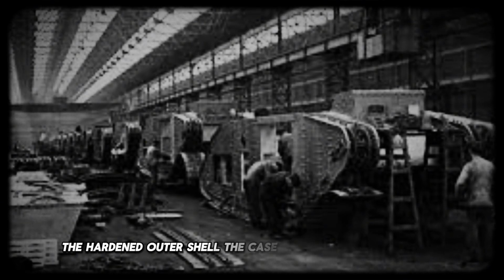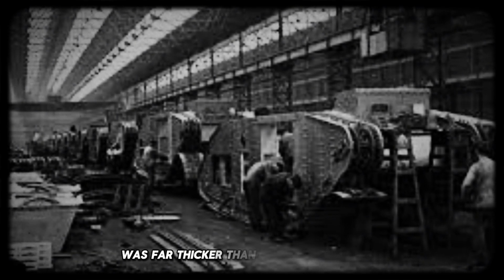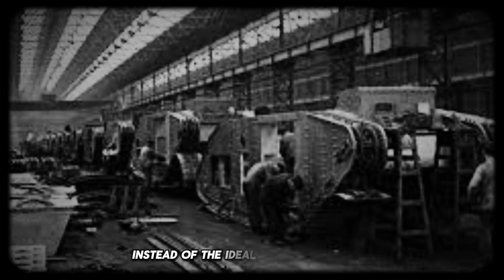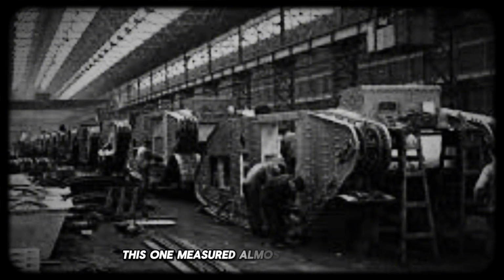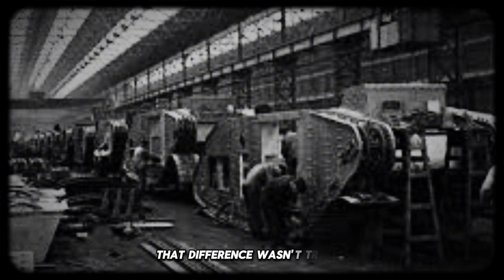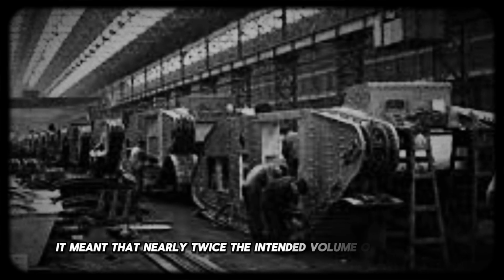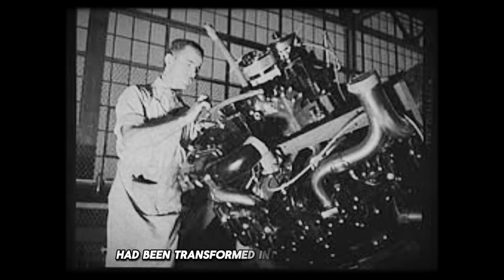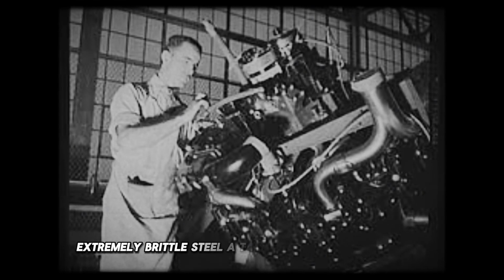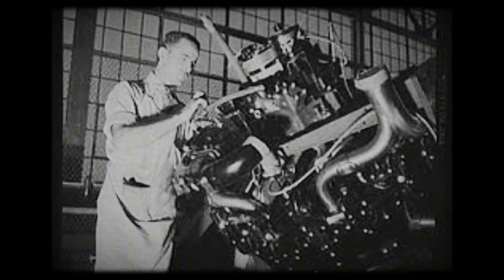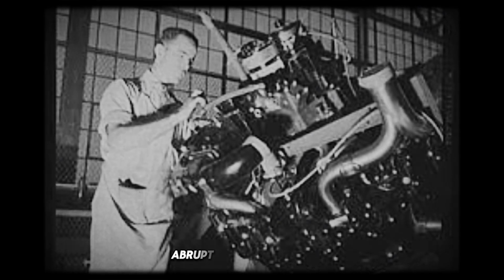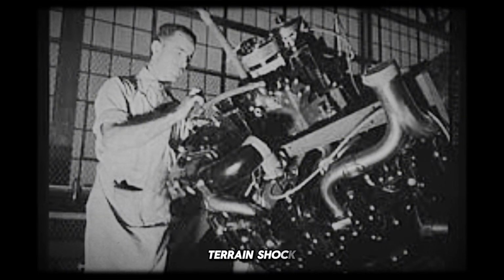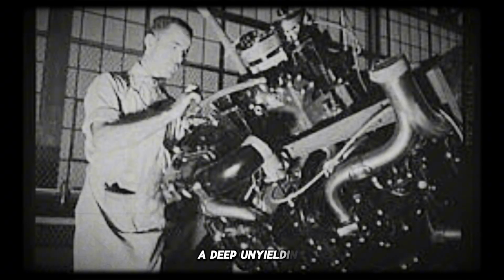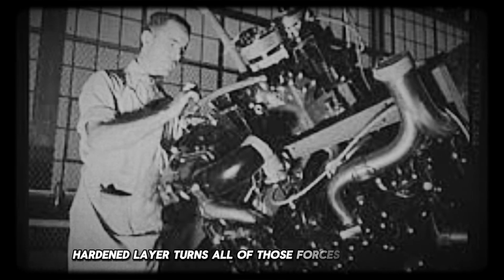The hardened outer shell, the case-hardened layer meant to resist wear, was far thicker than it should have been. Instead of the ideal 2 to 3 millimeters, this one measured almost 4.5 millimeters. That difference wasn't trivial. It meant that nearly twice the intended volume of the gear's surface had been transformed into extremely hard, extremely brittle steel. A tank transmission is punished constantly. Torque spikes, vibration, abrupt load changes, mud, terrain shock, and the violent jolt of shifting gears under battlefield stress. A deep, unyielding, hardened layer turns all of those forces into a danger, not a defense. To confirm the suspicion,